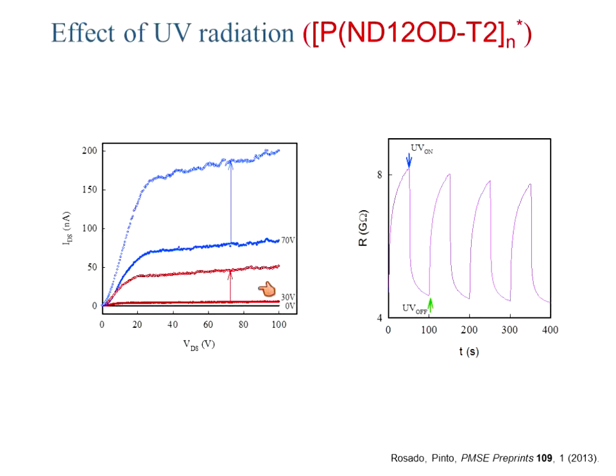But there is also, if you look at the FET device characteristics, you can see that at a fixed gate voltage of 30 volts, at a fixed gate voltage of 70 volts, the moment you put UV on, you basically increased the device current, which means that you have increased the transconductance of the device and improved the mobility. This has to do with UV creating an electron-hole pair in the polymer. Then the hole combines with any adsorbed species like oxygen and removes it from the system. So it basically releases an electron that can then contribute to the flow of current in the channel.